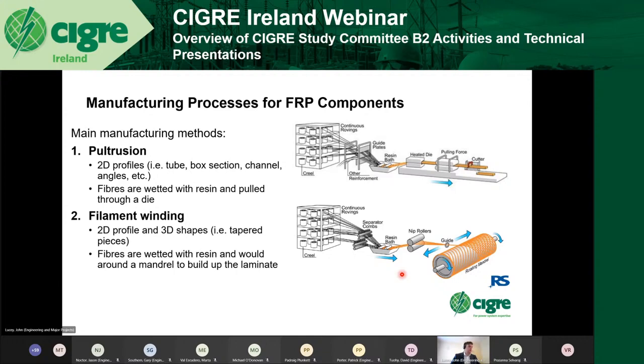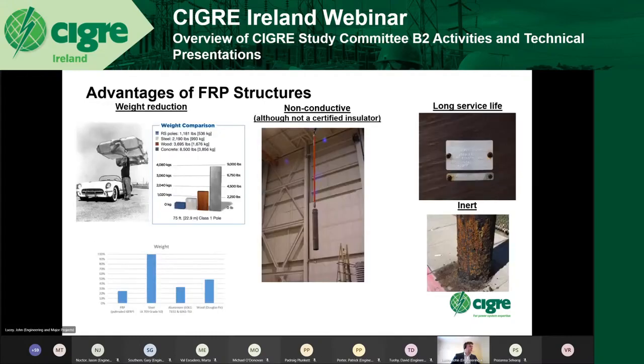The big disadvantage, obviously, is it's more of a stop-start process in comparison to the pultrusion, where once you have it wound on the mandrel, the mandrel has to be taken away and cured, and the fibres cured, so it's much more stop-start. So the filament wound is more expensive, inevitably, than the pultrusion poles.